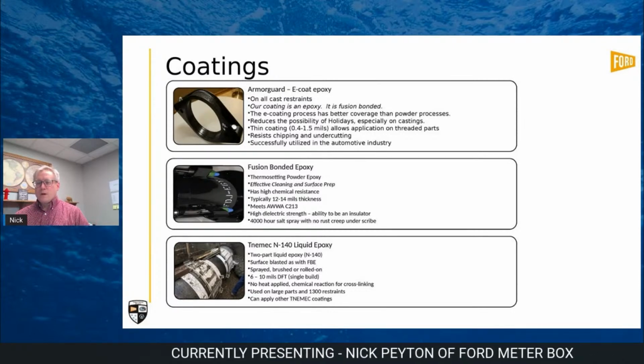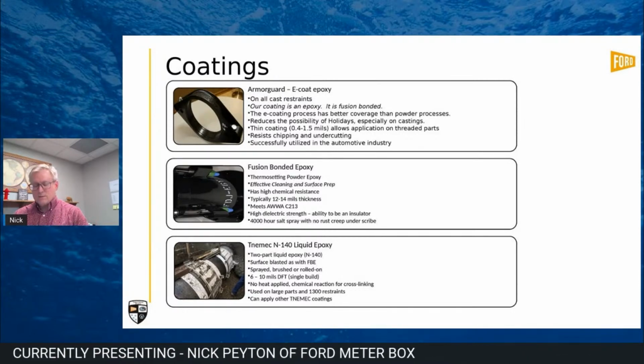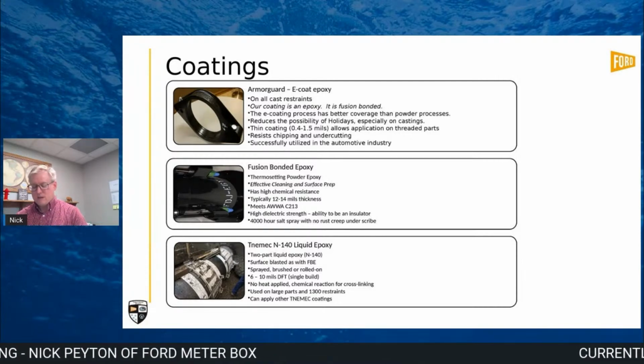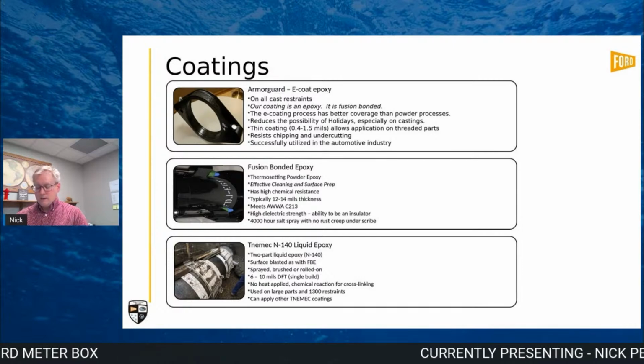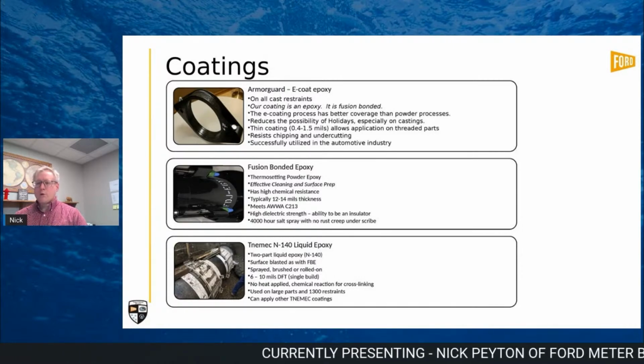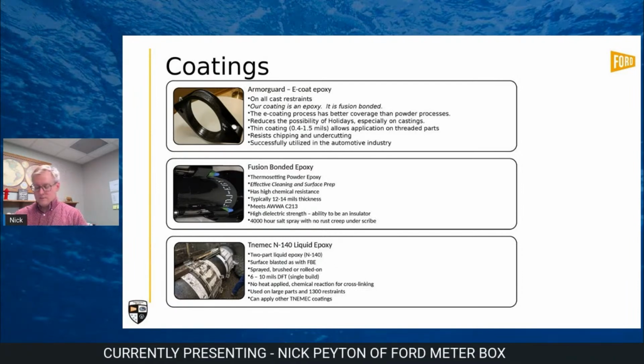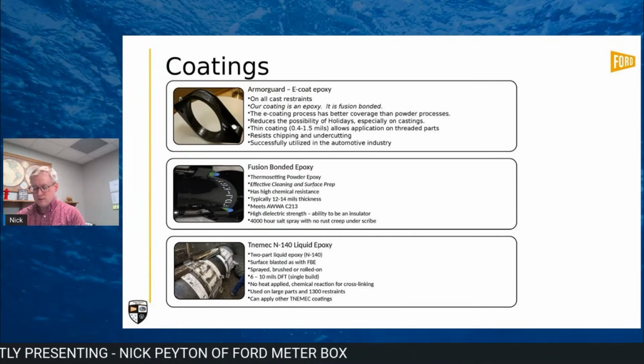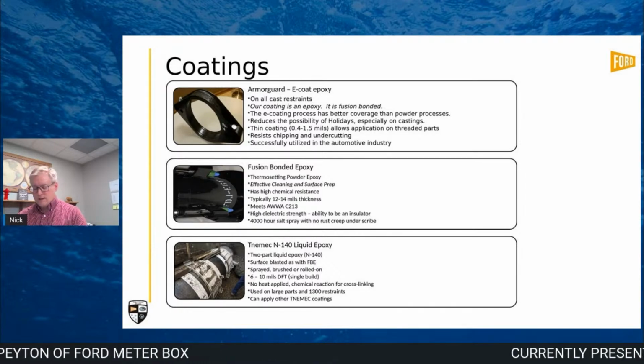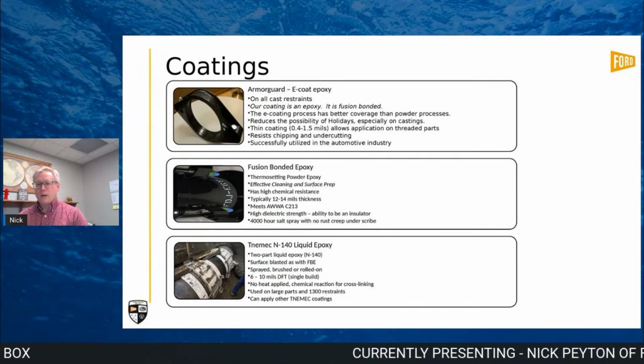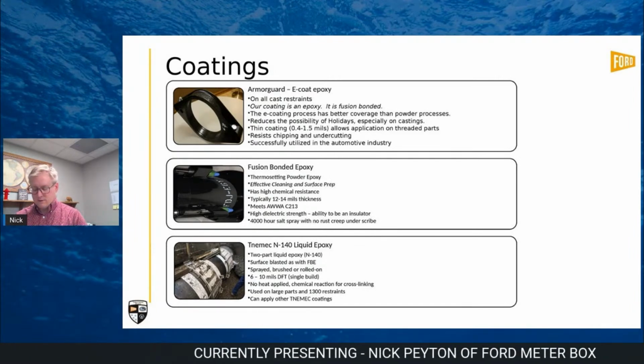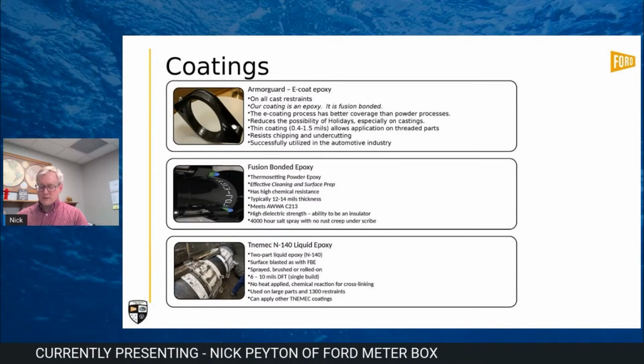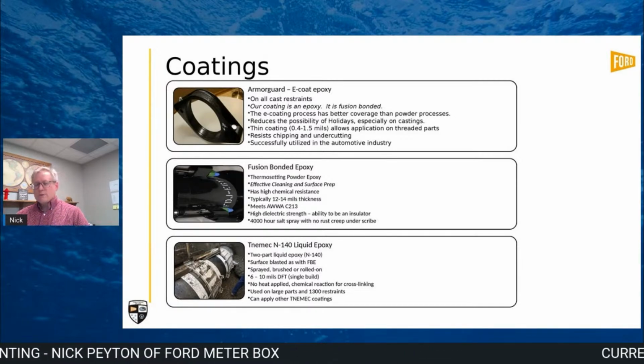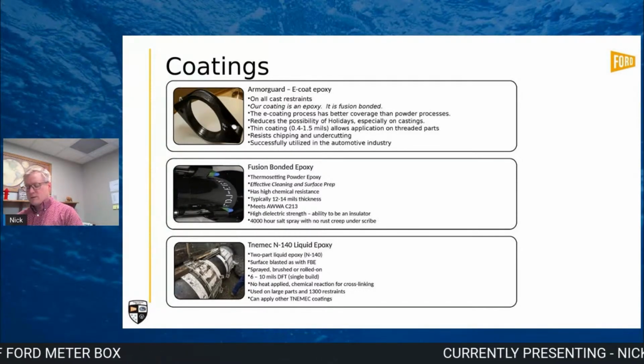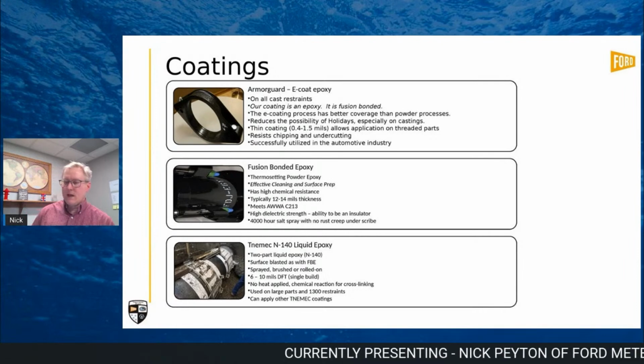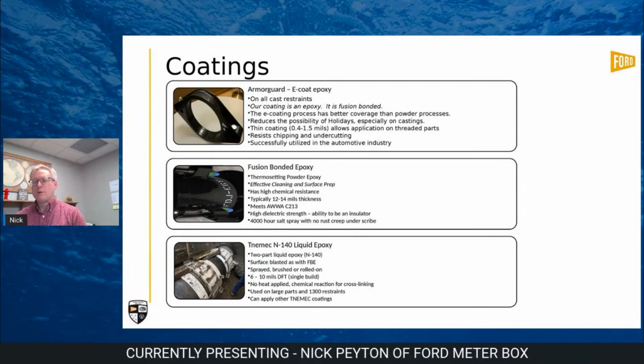Another is the FBE or fusion bonded epoxy. And in that process, you have to heat your casting up and then you apply a thermosetting powder epoxy. Now, a critical requirement of that particular coating is the cleaning and surface preparation. And when done properly by blasting and getting a near white finish, you've applied the thermosetting epoxy. The end result, you get anywhere from 12 to 14 mils thickness of the coating. And again, that's going to give you good, solid corrosion protection.